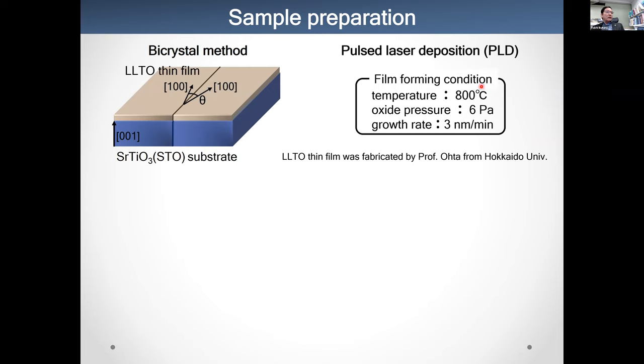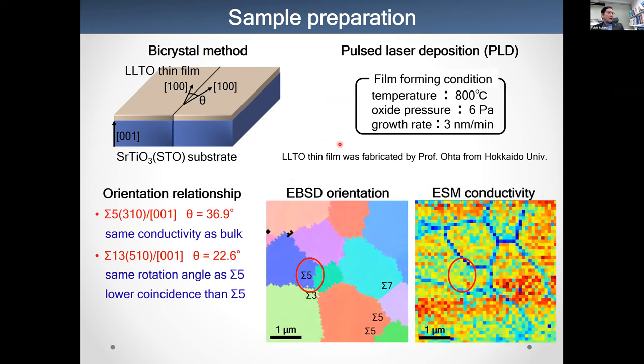is shown here, 800 degrees C. This is a collaboration with Professor Ohta's group at Hokkaido University. We fabricate the sigma 5 boundary, where the misorientation angle is 36.9 degrees, and also the sigma 13 grain boundary, where the misorientation angle is 22.6 degrees. The rotation axis is the same as sigma 5, but with lower coincidence than sigma 5. Then it is very interesting to compare the structure and the properties between these boundaries.